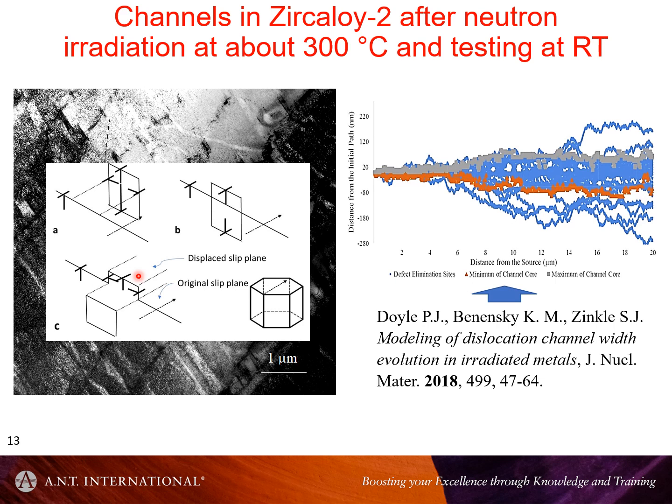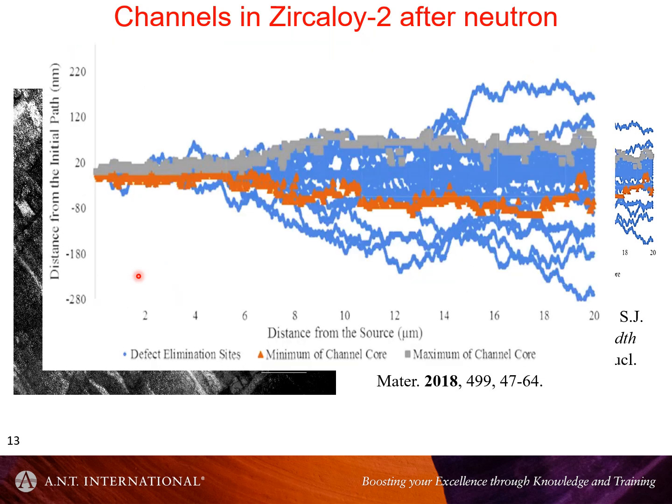A screw dislocation is just going to get hung up. This doesn't work for screw dislocations, it only works for edge dislocations. So what does that look like on this kind of diagram? Well, we start off, we have a source of dislocations here. They start out traveling at time step 1, for instance, and they spread out because they're absorbing loops, and they climb. And the direction of the climb depends on the sign of the loop, of course.